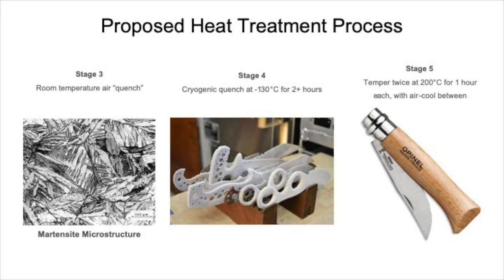The austenitic steel is removed from the furnace and allowed to cool in air until room temperature. Due to the alloying elements of the 440C steel, this cooling rate is sufficient to form a martensitic structure. Due to the high carbon nature of the steel, however, small pools of retained austenite are also formed throughout the material.